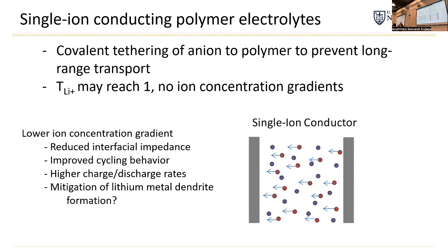So when the ion concentration gradient forms, the anions stack up at the electrode interface, and so this increases interfacial impedance. When they're up against the electrode interface, that's also where electrochemistry happens, so the anions can break, and this can create resistive surface layers. So you get better cycling behavior if you can mitigate this, if the anion decomposition is a bad thing.